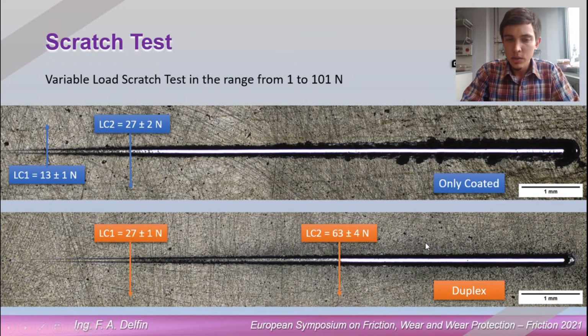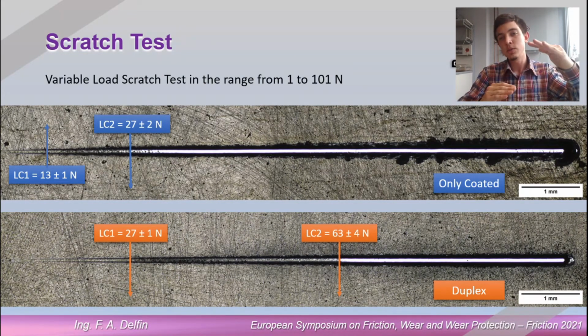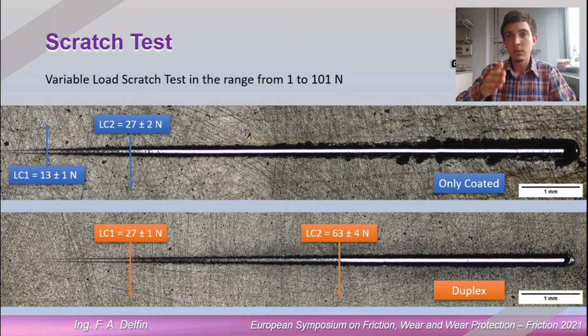applied here. So to get an idea, we have our metal with 350 HV hardness. We have our coating with 1200 HV, so this is a huge difference of hardness. But with the nitride before, we had like 600, 700 HV. And there is a gradient of hardness also because of the diffusion of the nitrogen inside the substrate. So it was for the better, and it helped to improve the adhesion of the coating.